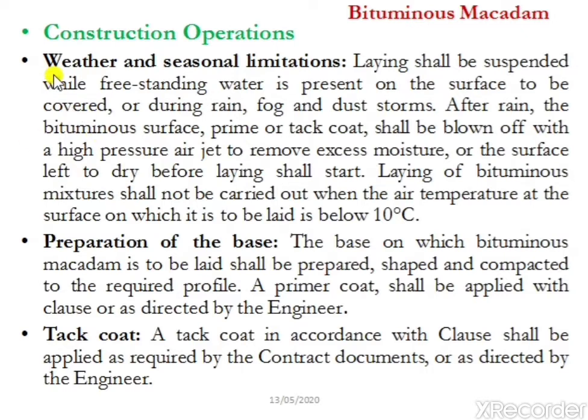The first one is weather and seasonal limitation. Laying shall be suspended while freestanding water is present on the surface to be covered, or during rain, fog and dust storms. After rain, the bituminous surface, prime or tack coat, shall be blown off with a high pressure air jet to remove excess moisture, or the surface left to dry before laying starts. Laying of bituminous mixture shall not be carried out when the air temperature at the surface on which it is to be laid is below 10 degrees Celsius.